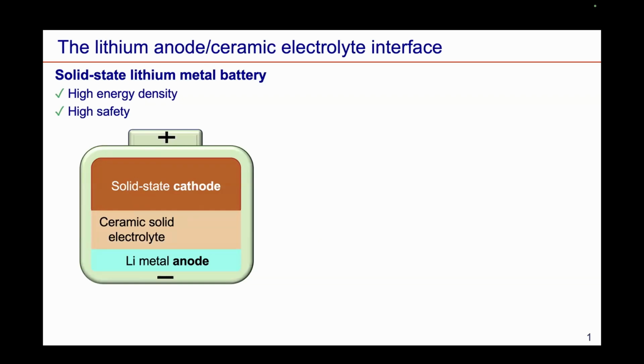Lithium-ion batteries are based on organic liquid electrolytes, which are flammable and raise quite a lot of safety concerns in practical application. In contrast, solid-state lithium metal batteries with a solid-state cathode, a ceramic electrolyte, and a lithium metal anode can fundamentally solve these safety issues and exhibit a significantly higher energy density. When charging this battery, lithium ions are extracted from the cathode and transported across the ceramic electrolyte towards the lithium metal anode, where they are reduced to form lithium metal. Discharging is the reverse process.